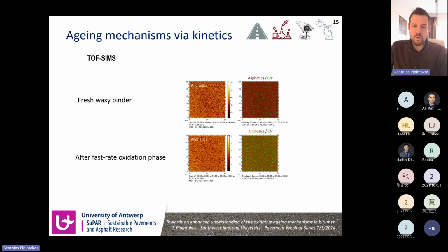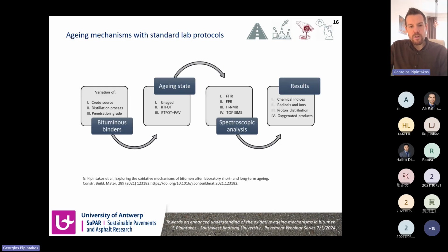And this, of course, also had some difficulties in identification, because the waxes were related with the aliphatics, obscuring the true impact of the chemical compounds for this waxy binder. However, in reality, as we know, we don't use aging kinetics in the lab, but rather standard simulations of rolling thin film oven testing, or RTFO, followed by pressure aging vessel, or PAV, that simulate the short and long-term aging.